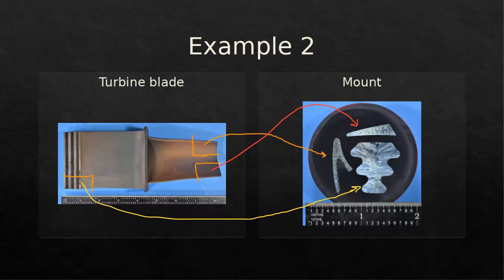But in order for me to look at whether or not I've got cracking in this dovetail region, I mounted it in the axial orientation. So this is the axial orientation. These other two, since I have to evaluate the coating, especially around the tip of the leading edge and the tip of the trailing edge, I need to mount those in the transverse orientation. So I'm looking at this surface right here on both of these pieces.